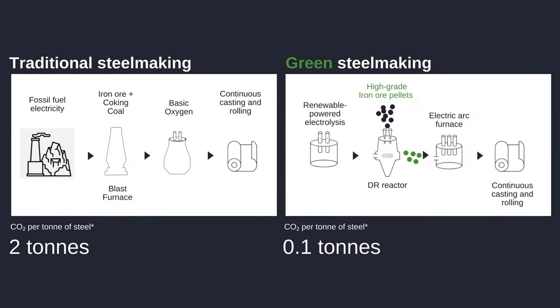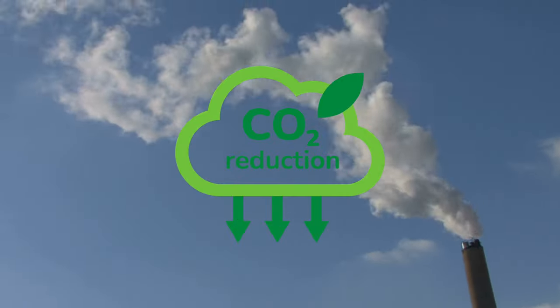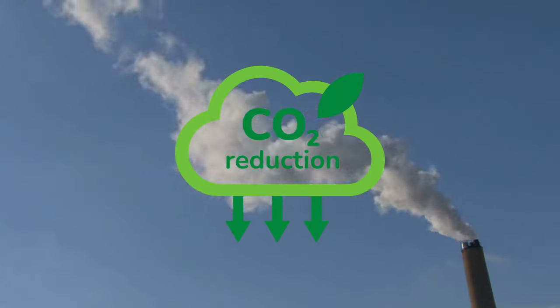Yeah, look, we're in a great position to have it a little bit both ways, because we start off feeding into the traditional steelmaking route with the high-grade direct shipping ore. But then beneath that, the magnetite ore, which is very high grade and upgrades very easily, we think, once we finish the feasibility studies, etc. That's a process where the higher the Fe content, the easier it is to make direct reduced iron. So you're basically jumping the blast furnace step, which requires the carbon import through coking coal.